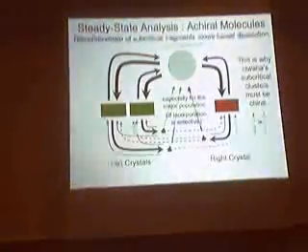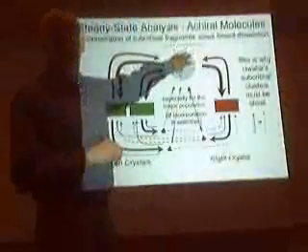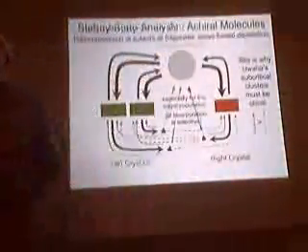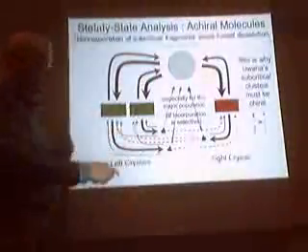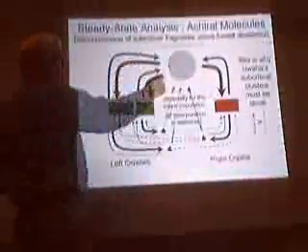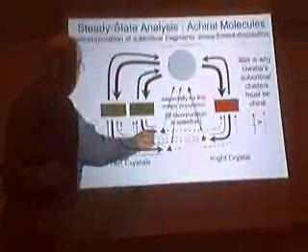Let me address that first, and then you can continue. Okay. In steady state, the rate off and the rate on are balanced. But the kinetic is the same. And the reason is that the concentration in solution adjusts to make this equal this. That's what a steady state is. If dissolution is faster than growth, this will build up until this becomes the same as that. Although with the ablation, you also have this channel. So in steady state, on has to be this plus this, but not this plus this, because you have this possibility. Does not mean that both processes are similar.